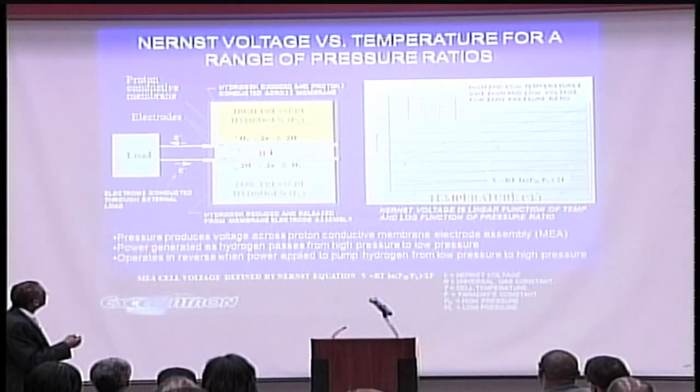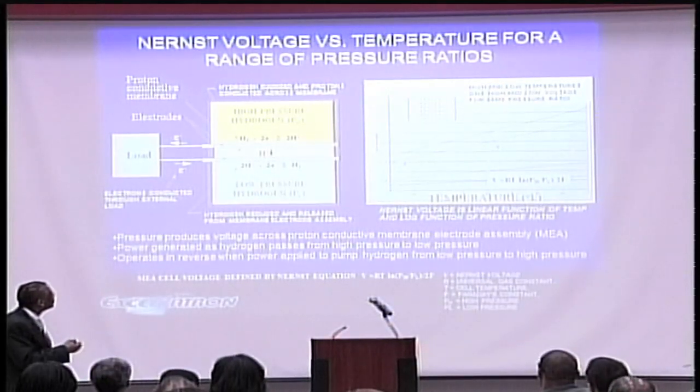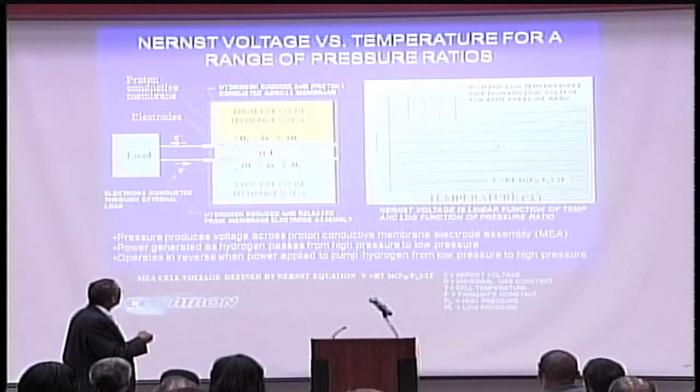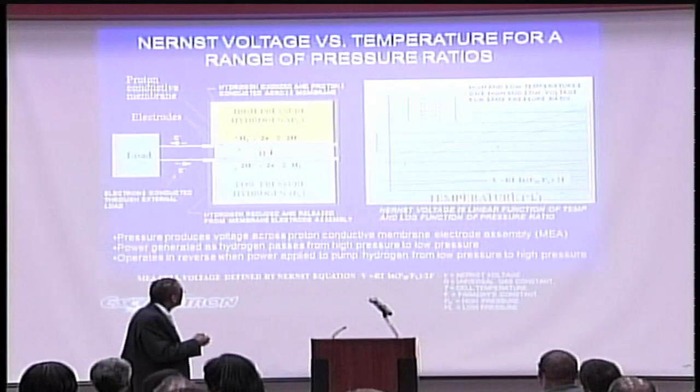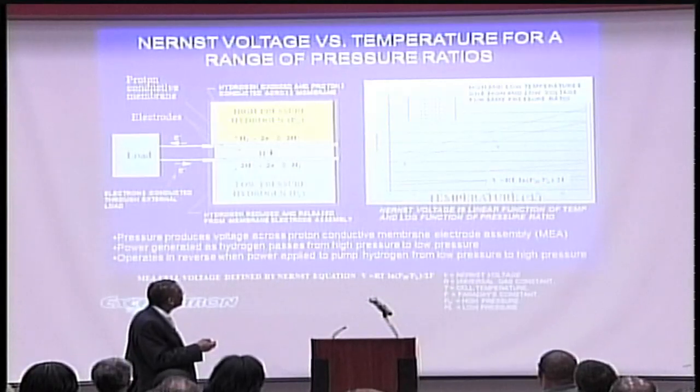Well, in this system, there's no oxygen and no water. You have high-pressure hydrogen on one side and low-pressure hydrogen on the other side, and the pressure differential forces the hydrogen through, gives you the current, and on the other side, you just reconstitute the hydrogen molecule. The voltage for a cell like this, called a hydrogen concentration cell, is actually given by the Nernst equation, and it's a linear function of temperature and a log function of pressure